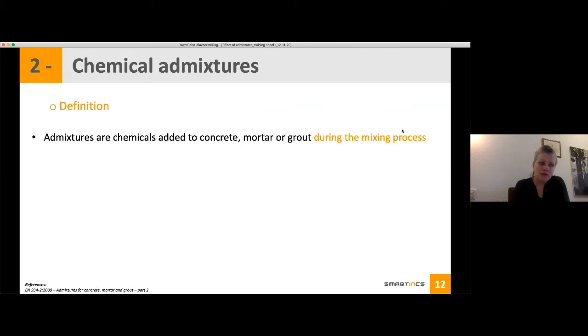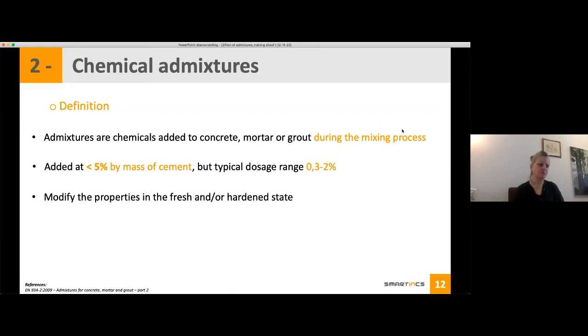According to the European standard, the admixtures are chemical, and what is important, they are added to concrete, mortar, or grout, cementitious material, and they are added during the mixing process. They can be added at different stages, but it's always during the mixing process, and they are added at less than 5% by mass of cement. So this is what is in the norm, but typically in practice, we add them at 0.3 to 2% by mass of cement.